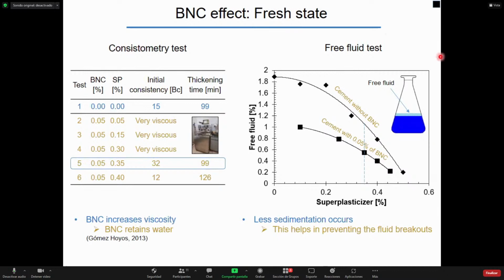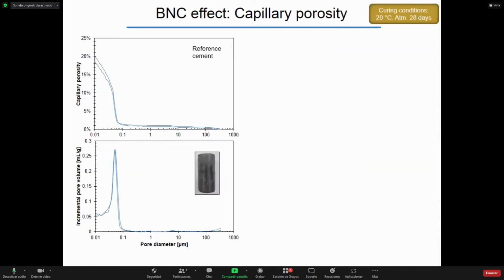However, when we add bacterial nanocellulose to the mixture, we see that it follows the same trend, but with lower amounts of free fluid, meaning that less sedimentation occurred, and that bacterial nanocellulose is helping in preventing fluid breakouts. Now that we have seen that bacterial nanocellulose modifies the fresh state, we will see how it modifies the hardened cement. We will study the microstructure of cement.